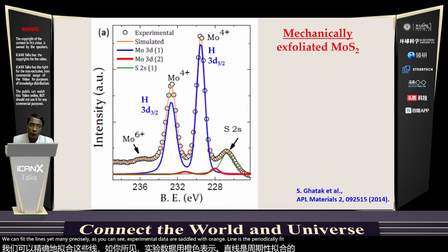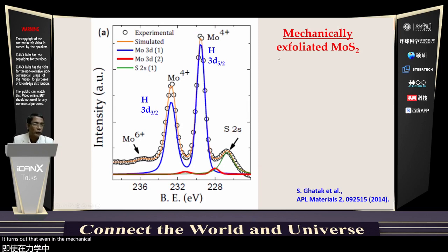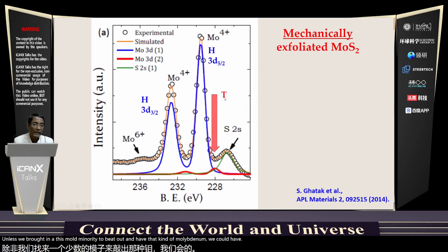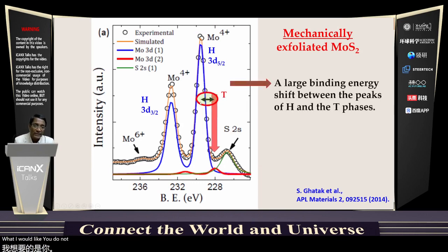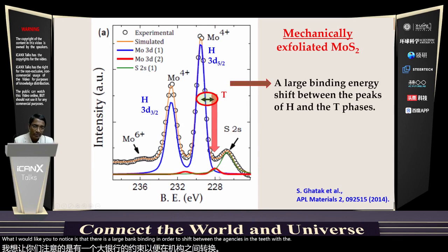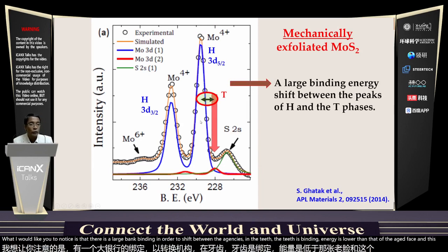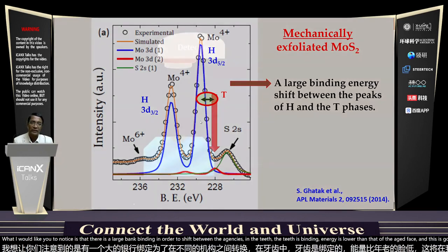It turns out that even in the mechanically exfoliated one, we couldn't fit unless we brought in this small minority peak of another kind of molybdenum, which we would have called at that time the T phase. What I would like you to notice is that there's a large binding energy shift between the H phase and the T phase. The T phase binding energy is lower than that of the H phase. And this is going to play a crucial role in what I'm going to say after this.